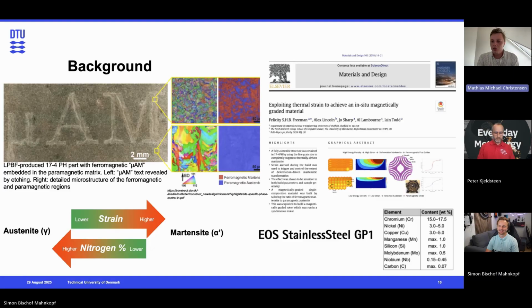Exactly. And just to say one thing more, Freeman, who is the author of the paper that we were very highly inspired by in terms of being able to generate this magnetically graded material, experienced these porosities that were causing a motor stator to crack. And so this is what we set out to solve: how could we do what she had done, while decreasing the amount of print defects, so we actually had a usable part that didn't have to be stabilized with epoxy, but could come off the build plate and be used in electromechanical or electromagnetic applications, such as a motor stator, which is a good example.